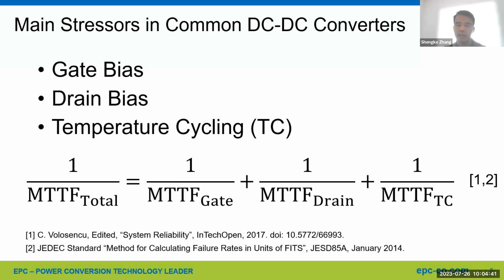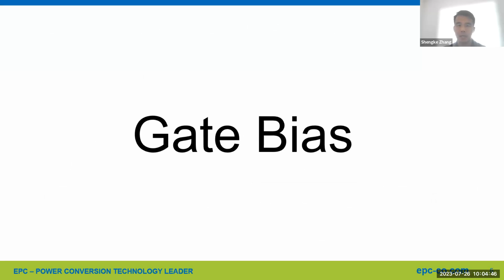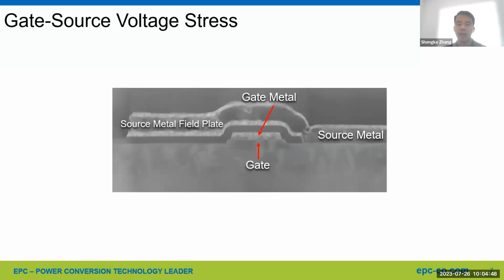So next, we will examine each stressor individually. Gate bias. To start off, let's look at our gate structure in this TEM cross-section image, where we can see the source metal, gate metal, source field plate, and the gate. You may notice a dark layer between the source metal field plate and the gate. This is a silicon nitride dielectric layer. Please keep this cross-section in mind because we will come back to this image when discussing gate failure mechanism.